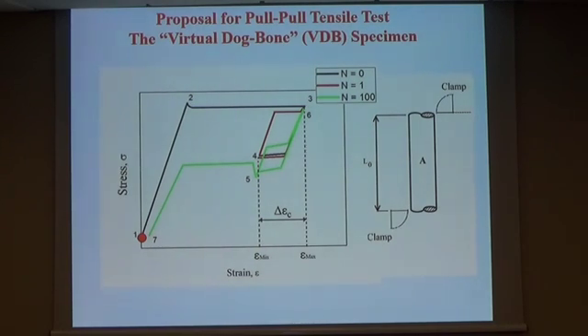We take advantage of the functional fatigue to localize an effective zone of the wire with functional fatigue. So the idea is to apply a near isothermal cycling, at a very low strain rate, so we are sure that we have an isothermal situation and the transformation initiates in this place. Here we have schematically the procedure. We have the elastic loading, then the peak stress to nucleate the transformation domain, usually in the clamp.